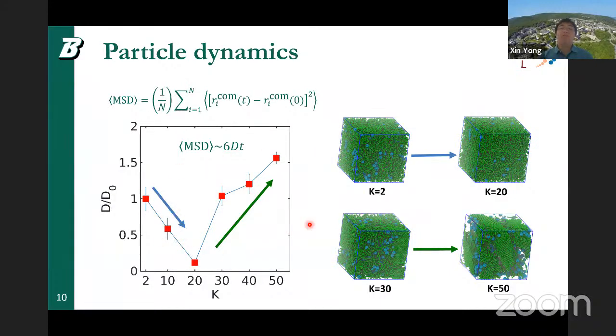And so this plot demonstrates the variation of the diffusion coefficient as a function of the rigidity of the polymer. One interesting observation here is that this variation is non-monotonic, which might be a little bit confusing. When we start to increase the polymer rigidity, the diffusivity first reduces. That means the polymer starts to suppress the diffusion, and the particles are more caged in the matrix. However, when the nematic order regions start to develop, we observe an increase of the coefficient.